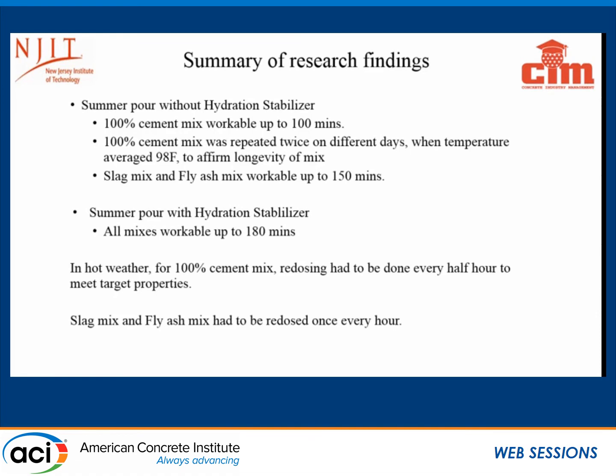Maybe it's a hydration stabilizer. I can tell you that in our area at 98 degrees, it likely may not work to maintain slump within 1 inch of batch slump at 180 minutes. It may take something like a slump extension admix. I'm not here to sell admix, just making a statement based off of data in our market. So I think that's a big thing to understand. We don't want to get into the business and have our customers get into the business of saying, hey, this is great, just keep adding admix every 30 minutes and you'll maintain something good.